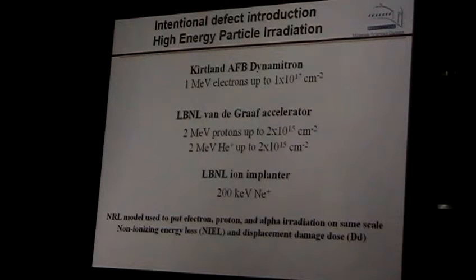And to do this, we have material, grown indium nitride or indium gallium nitride, and we intentionally introduce defects. The way to do it is you have high energy electrons, 1 mega electron volt, and you bombard your sample, and you're getting a lot of defects. You can use also protons, and you damage it even more, because the heavier the particle, the more damage. You can use even helium particles, and then they damage